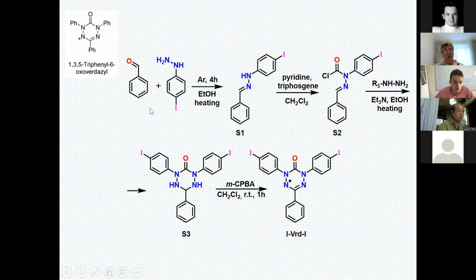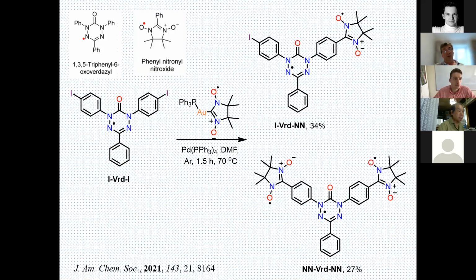Actually, we condense the corresponding iodide derivatives of phenylhydrazine with benzaldehyde, and then by several steps, as you see, we succeeded in preparing these diiodo derivatives of oxo-verdazyl. The next step was the same as for preparing the diradical. We used a cross-coupling reaction of this diiodo derivative with nitronyl nitroxide gold derivatives, and finally succeeded in isolating monoradicals and the diradical with 34% yield and the expected triradicals with 27% yield.